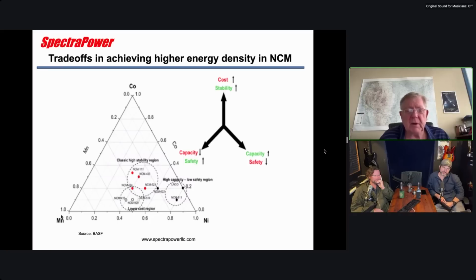That's because manganese is a lower capacity material, but as I mentioned, it has a problem where as you raise the temperature in the cell, it will dissolve in the electrolyte. From a safety perspective, that's a good thing. From a life perspective, it's a bad thing. And then nickel, which you really see increasing amounts of, even 95%. Nickel traditionally has been less safe, and there are people trying to make pure nickel cathodes and solve the safety problems at the same time. So the capacity goes way up as you go to high nickel, but the safety goes down correspondingly. And so that's been a challenge.